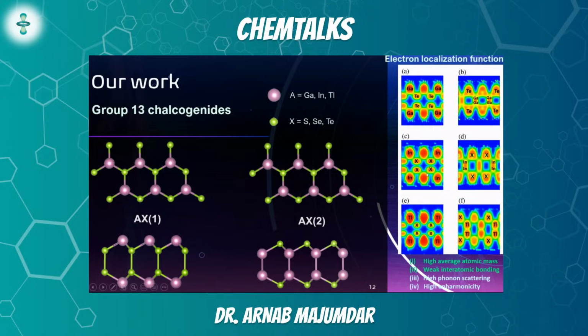But if we look at AX1, that is figure C, between the two chalcogen atoms in the middle layers, it is green. That means the bonding is quite weak. That is exactly what we want. That means just by looking at this electron localization function plot, I can predict qualitatively that maybe my elastic constants will also be low for the AX1 structure compared to the AX2 structures. Let's check that.